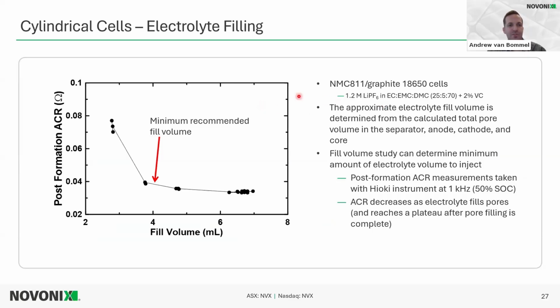Here are some examples of electrolyte filling and how electrolyte filling is done in cylindrical cells. So these are NMC811 and graphite 18650 cells. The electrolyte is shown here. Initially, the approximate electrolyte fill volume is determined by calculating the pore volume of all the materials. So this would be the separator, the anode, the cathode, and the mandrel volume, or the core volume.